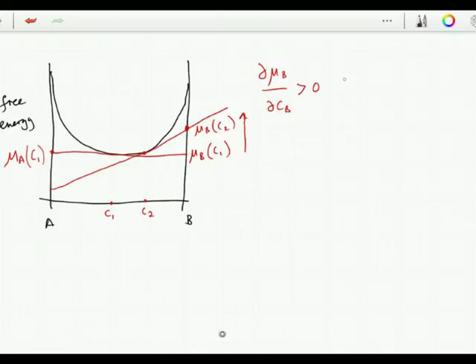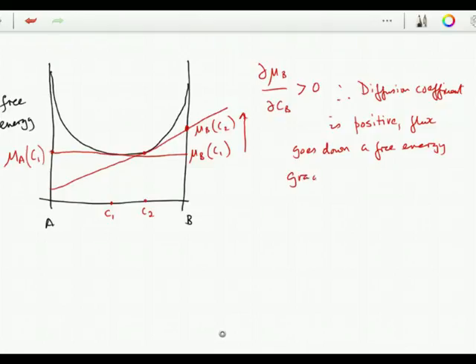Therefore, the diffusion coefficient will be positive, and the flux will go down a free energy gradient and down a concentration gradient, as in Fick's law. So this kind of a situation arises when A atoms prefer to be next to B atoms, and therefore we have a free energy minimum when we have a good mixture of A and B atoms.